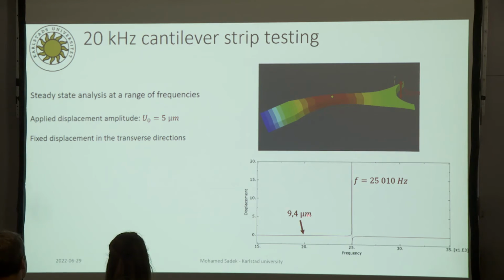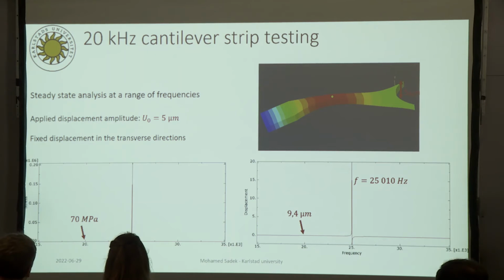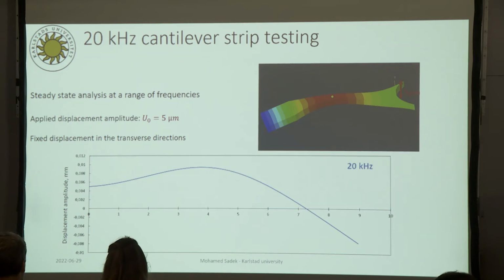So at 20 kHz, we should expect 9.4, approximately double the U0. If you look at the stresses, we should expect something close to 70 megapascal at 20 kHz in the same point. And at 20 kHz, this is the shape of the specimen according to the FEM model. It's back and forth, so this end is where the horn is clamped, and you see there's zero angle going out from the horn, as it should be.